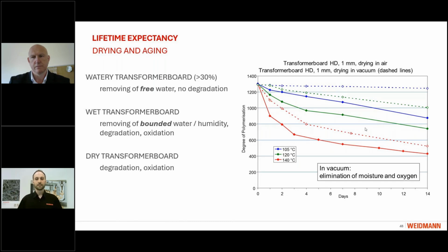The dashed lines show the vacuum state, and as you can see, at 140, our degree of polymerization just drops because we have a large contribution from pyrolysis. If we reduce temperature, we can reduce this effect. And secondly, if we compare vacuum to forced circulation, we of course can see that in vacuum there is no moisture and there is no oxygen. So any moisture that is present will be sucked out, any oxygen that is present will be sucked out, and therefore hydrolysis and oxidation are slowed in the rate.